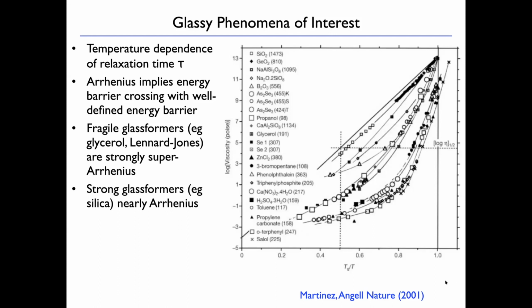So this is a plot of viscosity, but it just tracks relaxation time. So you can read it as a plot of the log of relaxation time versus one over the temperature, similar to what I showed you before. Okay. So a straight line on this would be Arrhenius behavior, which means that the relaxation time just goes like e to the some energy barrier over temperature, and that energy barrier is well defined. It's a constant. Okay. So that would be a straight line on this plot.